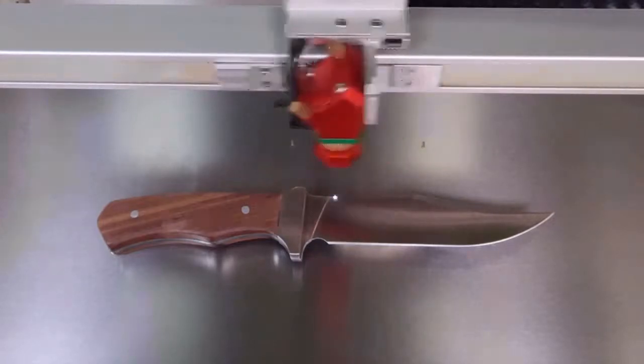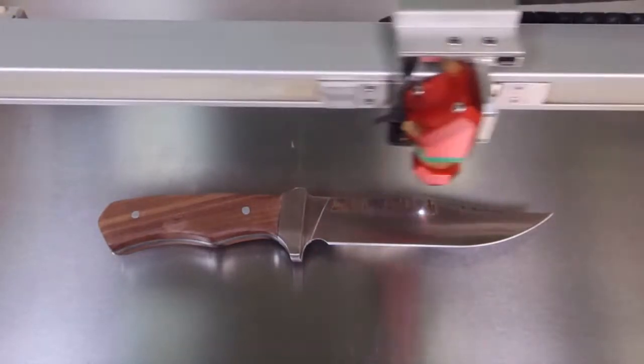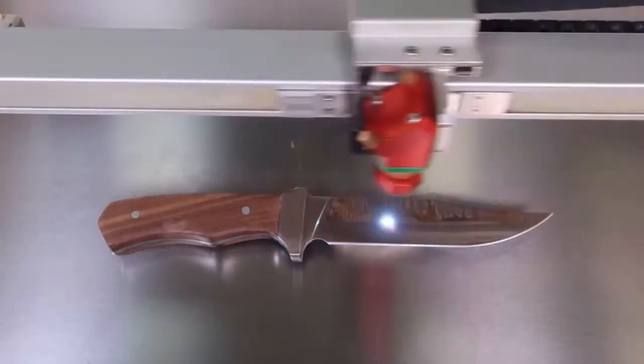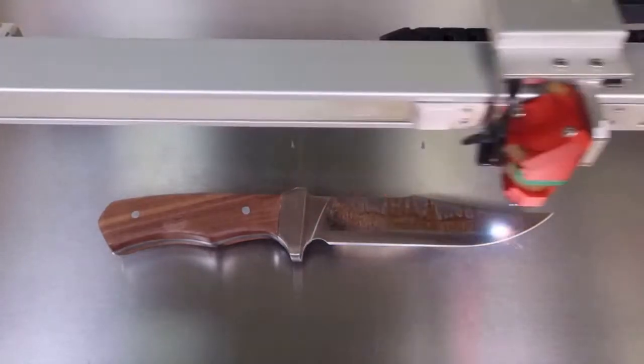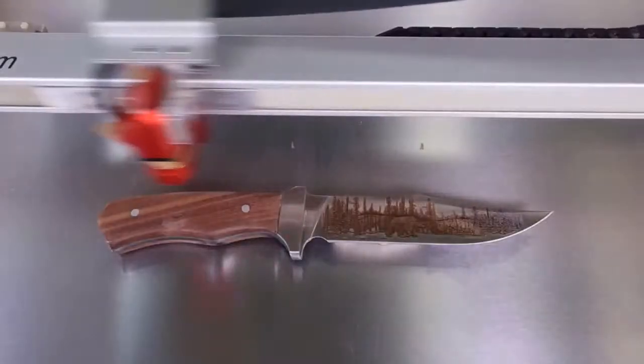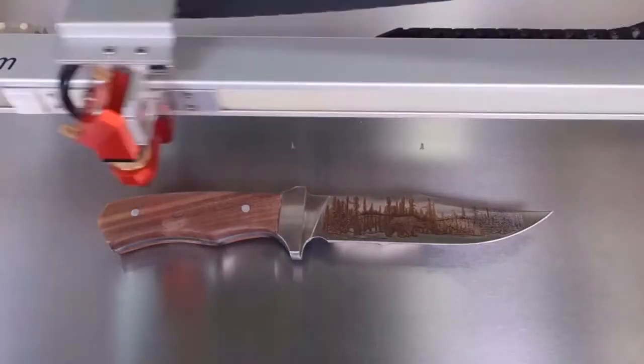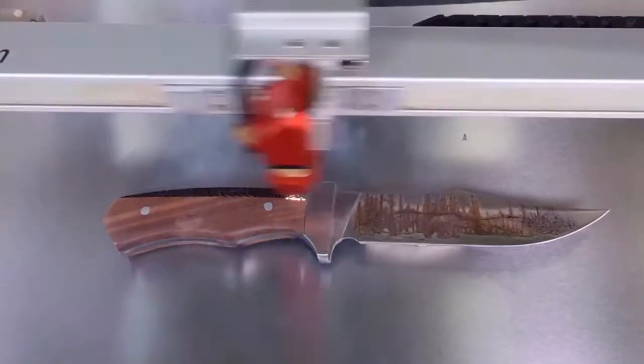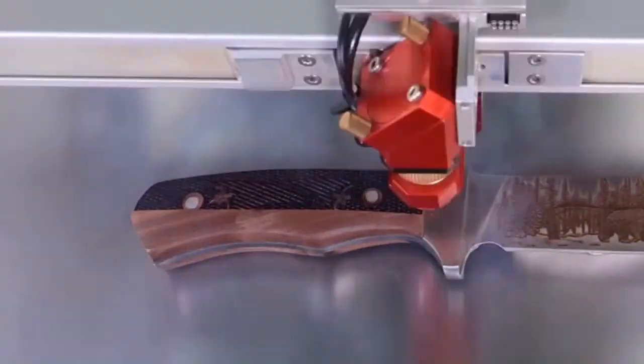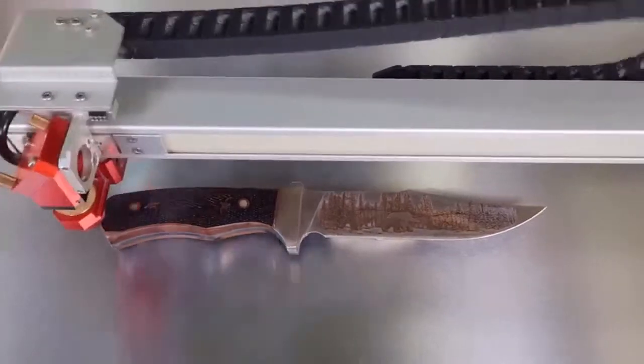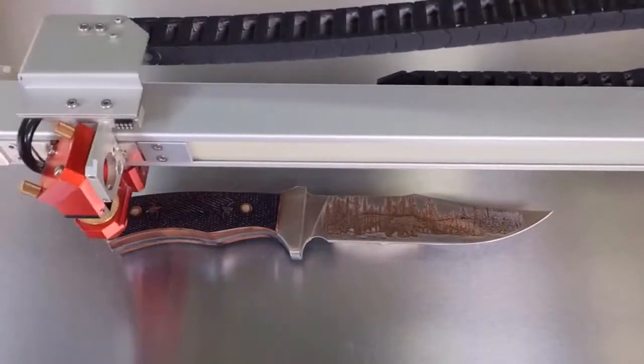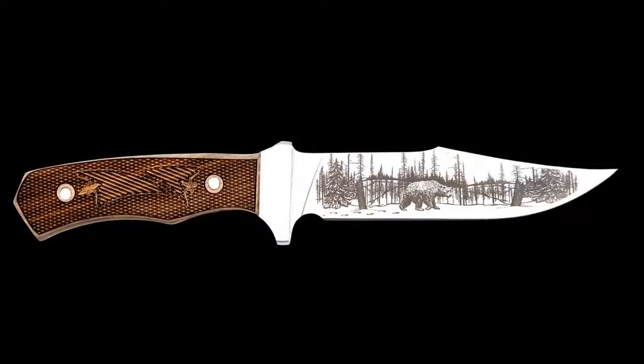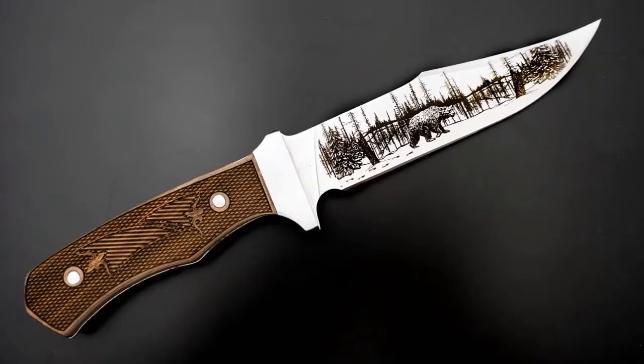And the blade is, of course, going to give us the contrast, direct mark into the blade itself with the fiber laser. And then the CO2 laser is going to, of course, etch the black color, which is the grip pattern in this case. So by combination of both wavelengths onto one product, just a beautiful application capability, and then also adding the gripping ability to use the checkering or 3D pattern relief mode also onto that. Little scrubbing with some water, put it in a photo booth, and you get this finished result here.